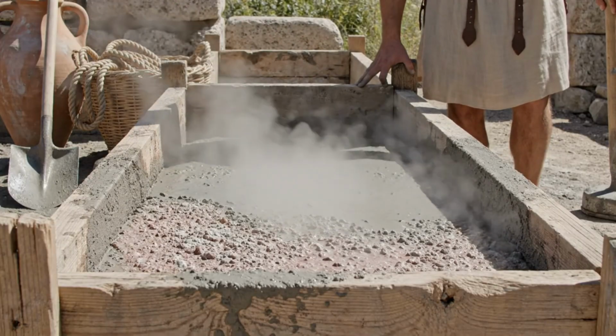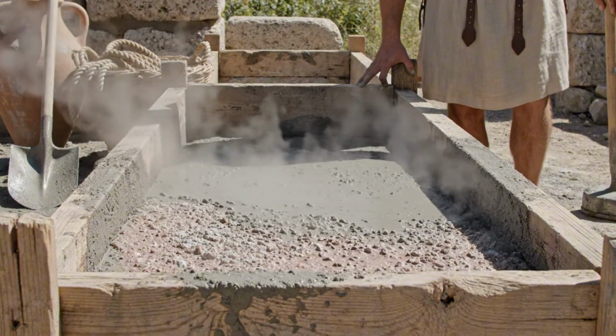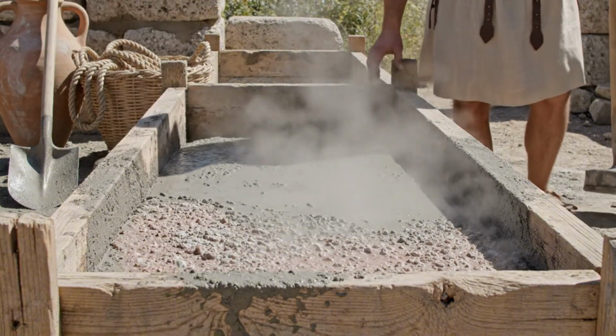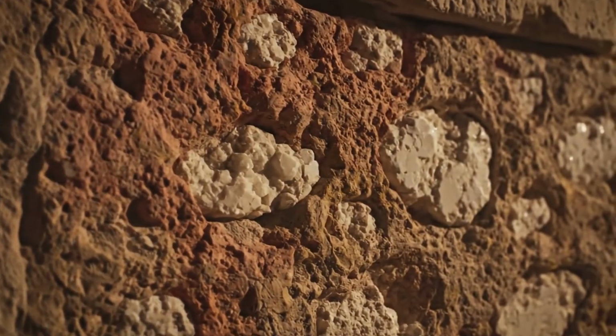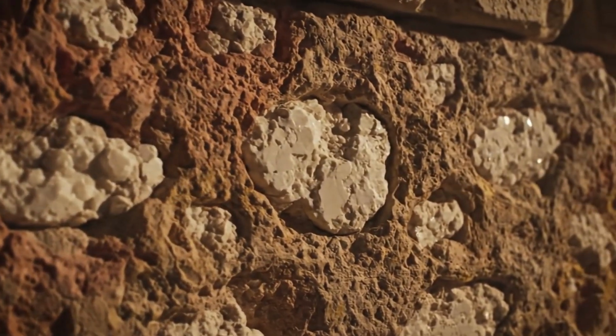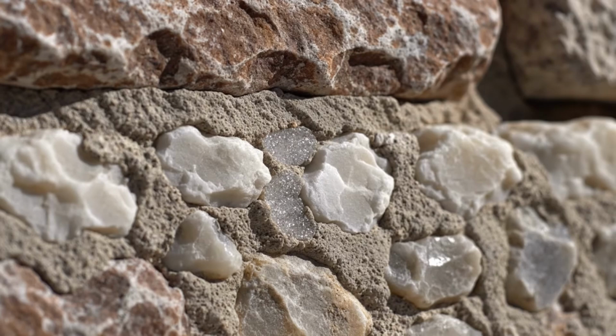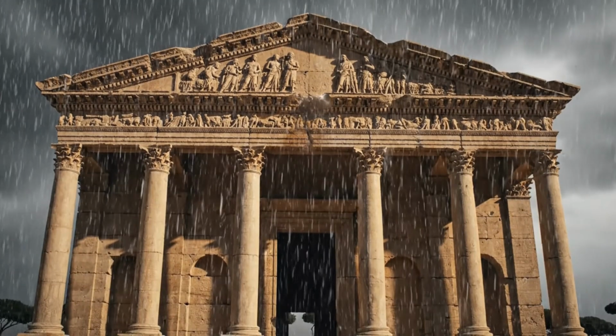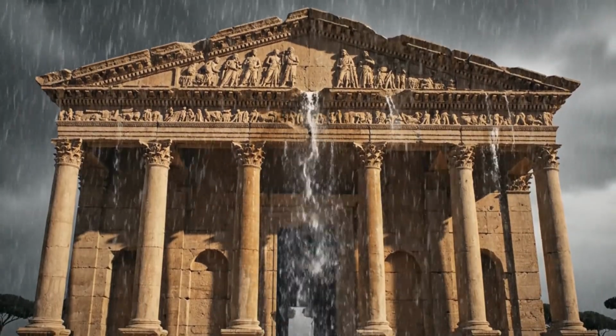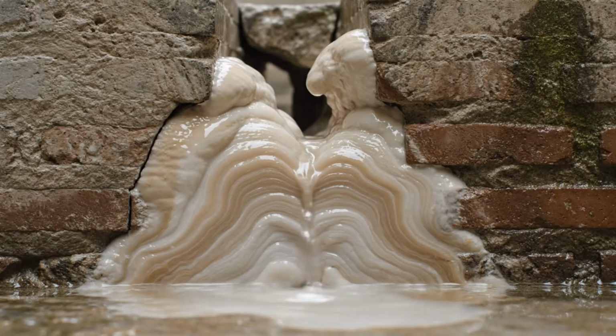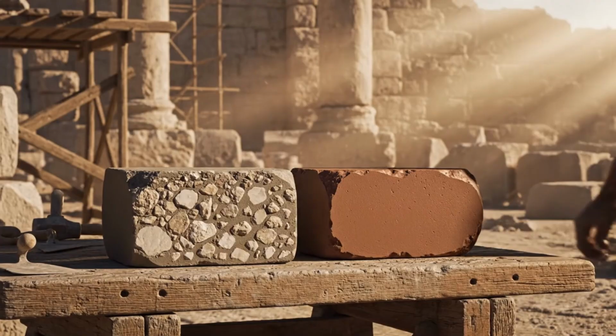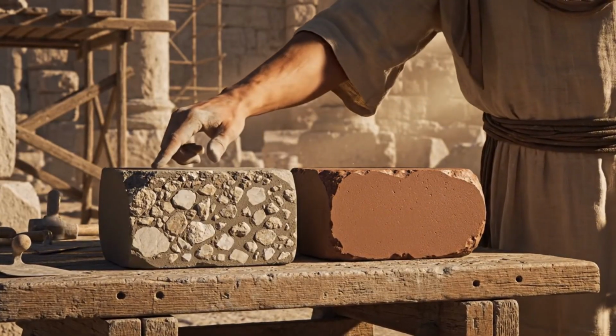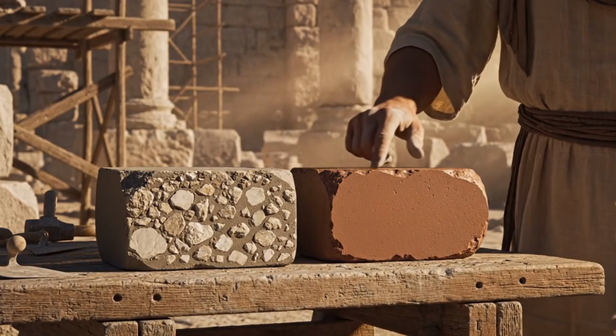Quicklime reacts exothermically when it comes into contact with water, generating significant heat. That elevated temperature within the fresh concrete would have enabled chemical reactions that do not occur under cooler conditions. The researchers concluded that this hot mixing process likely accelerated setting times and led to the formation of high-temperature associated compounds within the material. Within the lime clasts themselves, the hot mixing created a distinctive brittle and nanoparticulate architecture.